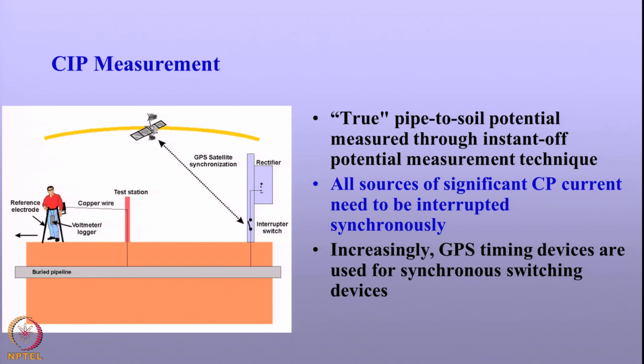In CIP measurements, we need to look at one important factor, that is, you need to measure the true potentials, that is, the true pipe to soil potential. You have to discount the resistance offered by the soil, that means you use the instant off potential measurement technique. What is seen in this diagram is various features associated with measuring the instant off potential for a given pipeline. In this case, you have a test station, a copper wire is taken from the test station and connected to the voltmeter. And the person carries the voltmeter, as you can see here, and it also has a data logger which records the volts at a given place.